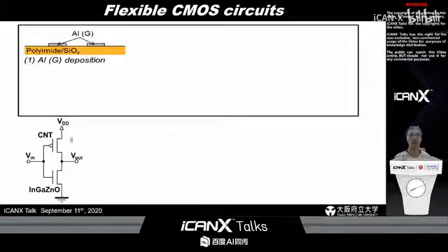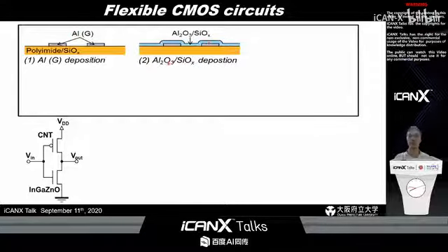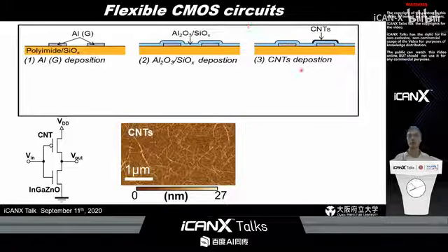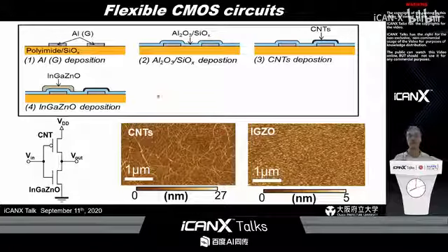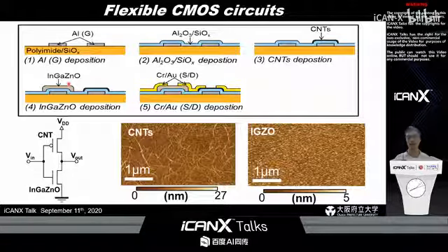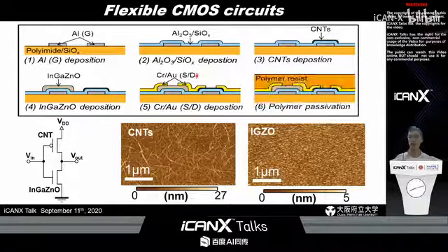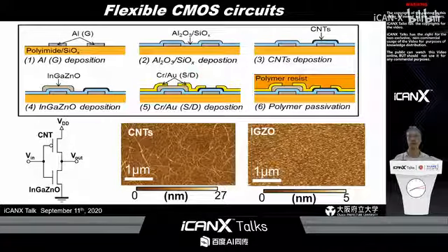Here, first, we use a polymer substrate, and then we deposit aluminum as a gate electrode. And then we deposit aluminum oxide as a gate dielectric material. Then we use carbon nanotube network deposition, like these networks, for the P-type transistors. Next, we deposit indium gallium zinc oxide using sputtering techniques to make N-type transistors. Then we deposit a source drain electrode of gold. And then finally, we deposit a passivation layer of polymer over the transistors.